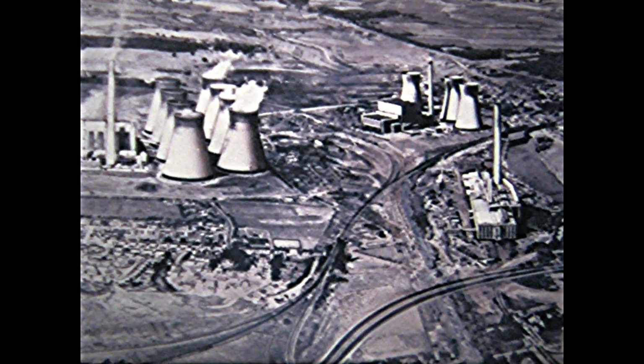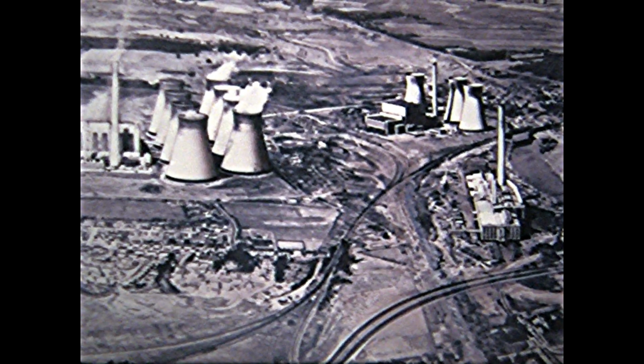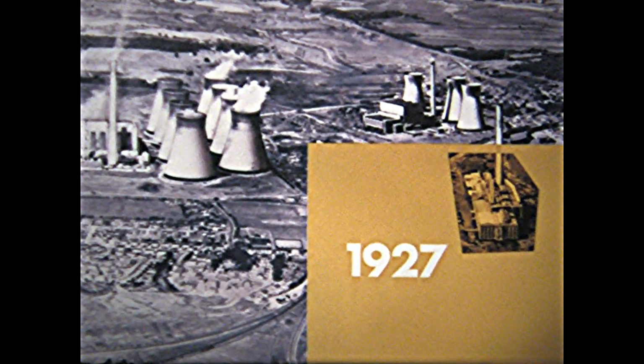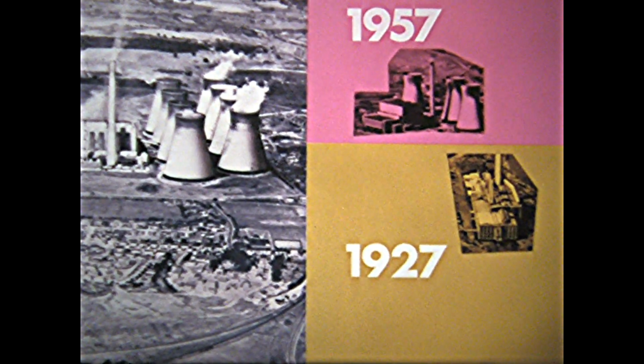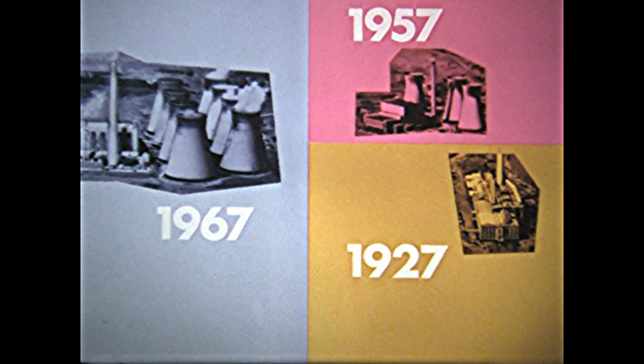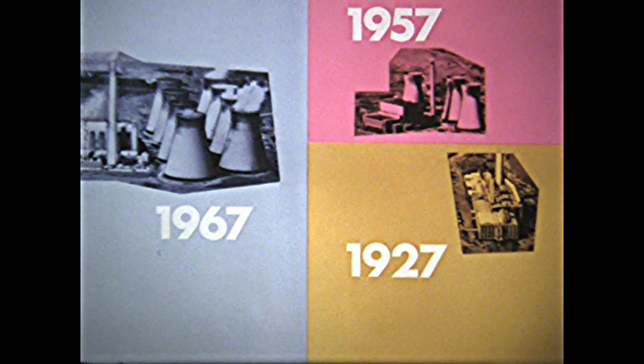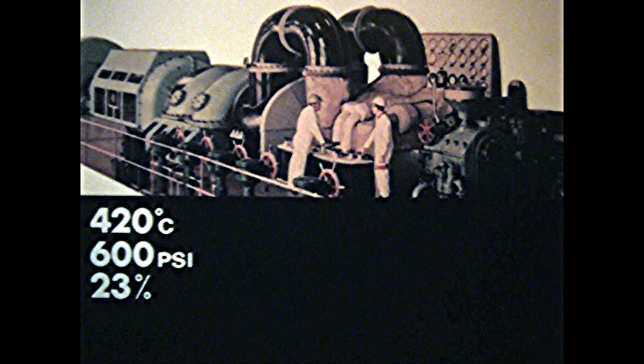On this site are 3 generations of power stations spanning 40 years. Each in turn has used steels that were successively developed to stand greater pressures and to work at higher temperatures. In a typical station around 1927, maximum steam temperature was 420 degrees. Maximum pressure, 600 pounds per square inch. And the thermal efficiency was only 23%. Output was 42.5 megawatts.